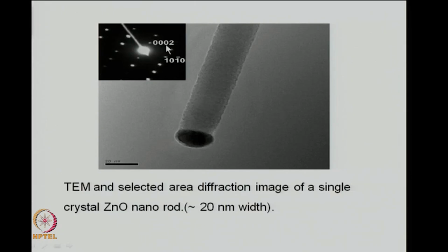And what you are seeing are called the HKL indices. However, most of the time we have 3 indices. Here, as you can see, there are 1, 2, 3, 4 indices. That is because this is a hexagonal crystal system. Zinc oxide crystallizes in the hexagonal crystal system. In the hexagonal crystal system, instead of defining each plane using 3 indices, we can define certain planes with 4 indices, and that is what has been done here.